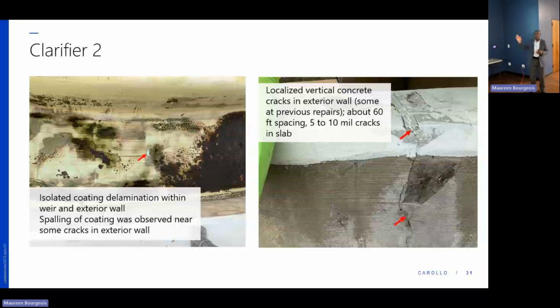Given of this acid to attack, we can see that they result in the paste erosion that we are seeing on the right, quite extensive, at least at the top 2 to 3 inches. Towards the bottom, very much less because that's also managed, but at the top where the environment is aggressive, above the water line, that's very visible.